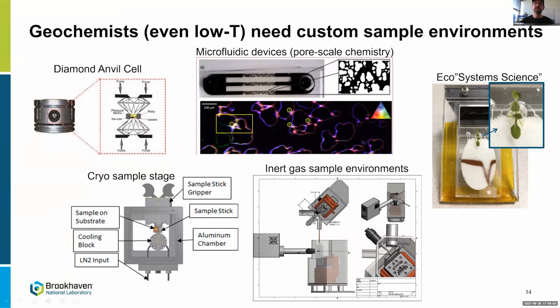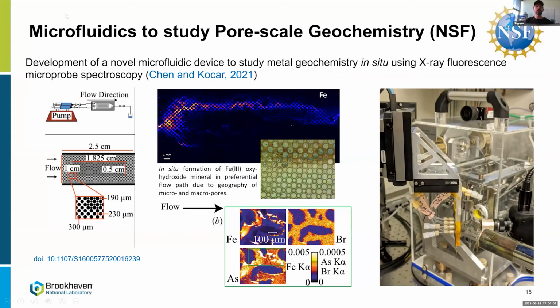In fact, let me just give you a few flavors of the work that's been going on in the custom environment. So here's one I just want to quickly point to, and if you're more interested, follow up with this paper by Chen and Kocar. But they're using another type of microfluidic device that's been etched out of silicon, where they can make very tight constraints on the pore system and then do hypothesis testing. And in this case, they're looking at iron oxide precipitation in real time.